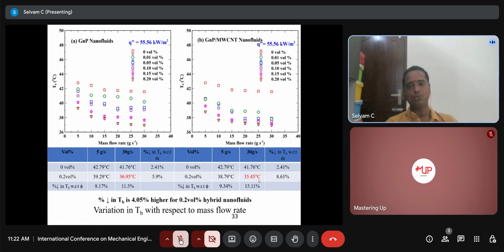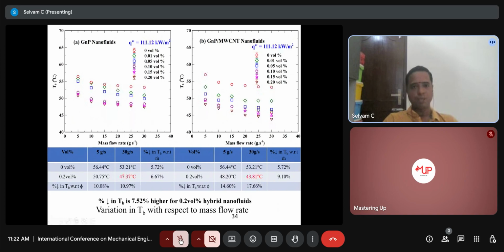At the same time, with the same heat flux condition, you can see the temperature variation when we are using the hybrid nanofluid. That time the temperature is decreased up to 35.45. The reduction percentage is 15.11%. So this shows the hybrid nanofluids are showing significant results as compared to mono nanofluids. And here also, we have increased the heat flux.